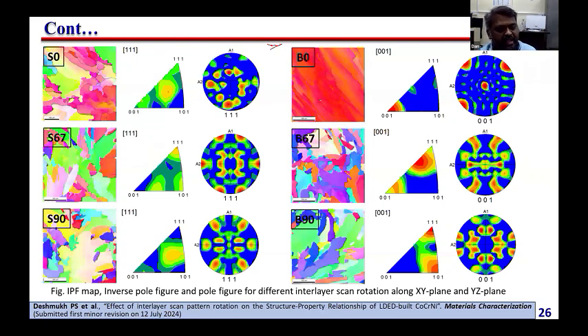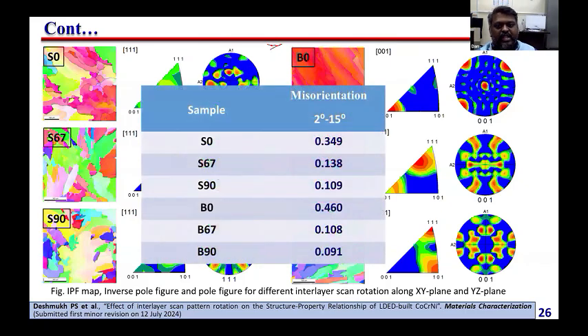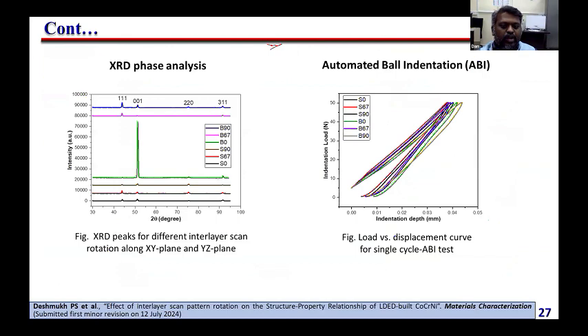Okay, so if you see the EBSD, here we can understand the microstructure and texture. Already I told, for the first case, the 001 texture, a preferred orientation, is forming, but 67 and 90 are forming a very refined structure compared to 0. Also the texture is quite different. There is no strong texture forming; we found different 111 or 101 fiber components. These are all the misorientations. The misorientation is also less compared to the 0 degree rotation. Already I told, the cooling rates are much better, so that's why the misorientation is reduced here.